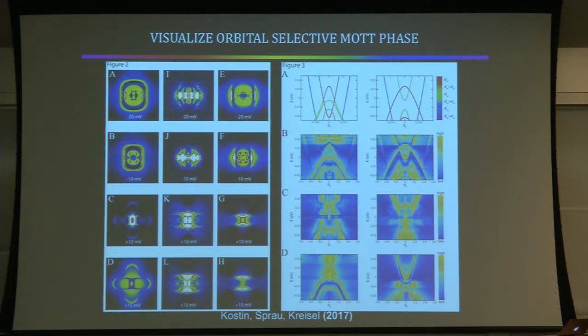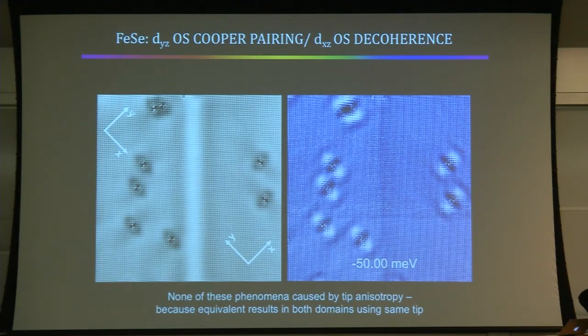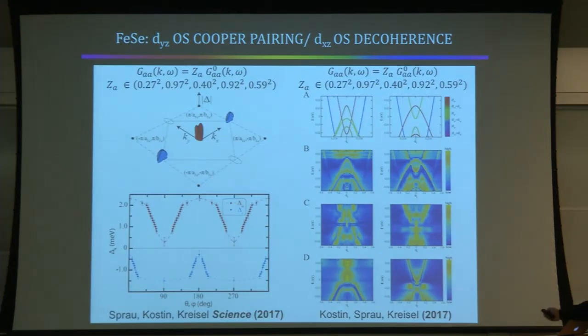So here's the non-orbital selective QPI. Here's the data. Here's the orbital selective QPI. Here's the non-orbital selective model. Here's the data. Here's the orbital selective model. The difference between these is that dxy, which is this thing, is knocked out of the scattering interference. All of these data are in very good agreement. We believe we're visualizing the orbital selective Mott phase. And we know that this has nothing to do with the tip, because we can do the same experiment over here and over there. We're in two different domains, but it's the same observer. So this has nothing to do with the technique. And finally, the ratio of these two numbers that we need to get the gap structure is within maybe 15% of the ratio of these two numbers that we need to get the normal state electronic structure. So that's our point of defense, that this is the correct argument.